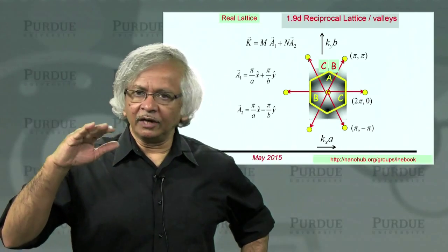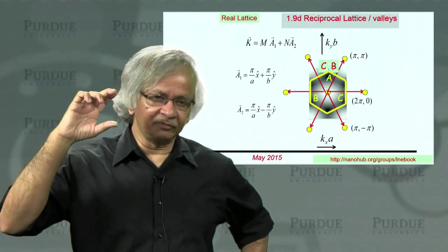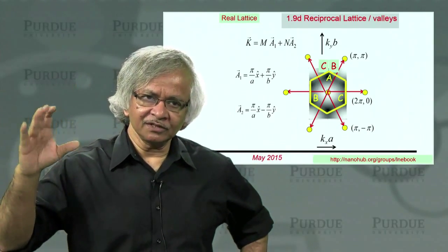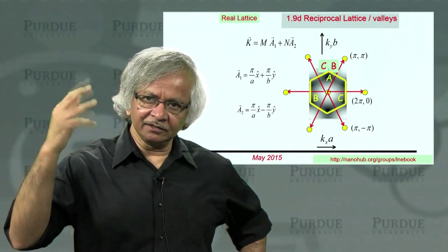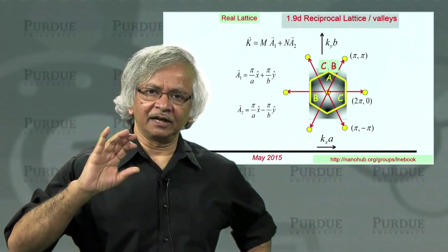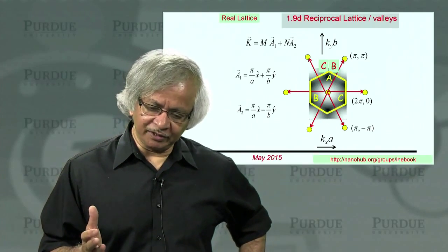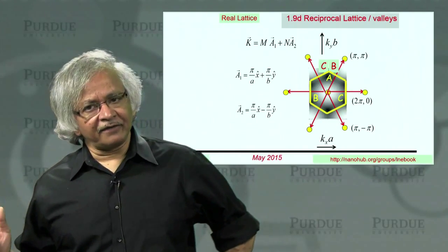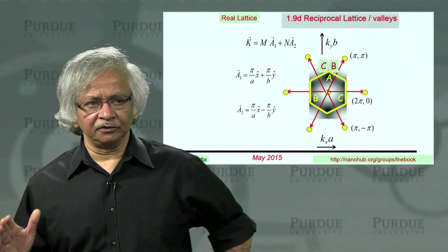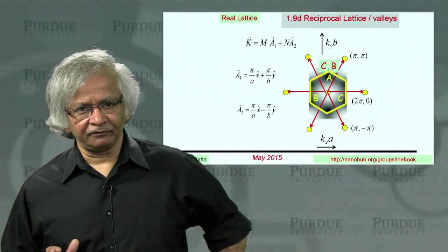Why 12.5? Well, the quantum of resistance is 25 kilo ohms. There are 2 spins in parallel. So 25 kilo ohms in parallel with 25 gives you 12.5 kilo ohms. That's the ballistic resistance usually. But when you measure it in graphene or in carbon nanotubes, what you get is more like 6 kilo ohms, half of that.